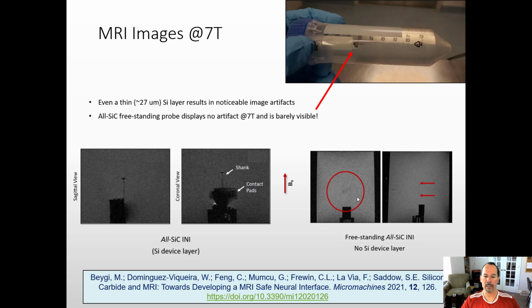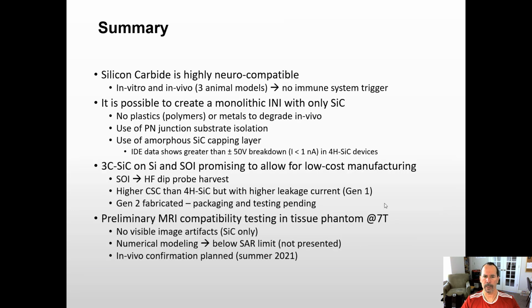When we removed the silicon, now we have just silicon carbide. Now we see barely any evidence at all that the probe's even in the tissue phantom. This is a gel tissue phantom with electrical properties to mimic that of the brain: permittivity, conductivity, and magnetic permeability. So we just published these results in Micromachines, and I encourage you to take a look at this because we're quite excited about this.